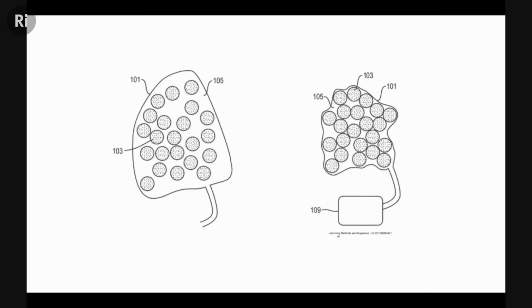Another phenomenon that we study in this phase change category is a principle called granular jamming. So granular jamming is like when you go to the beach and you jump on the sand and it's really hard, but when you play with the sand, it's really soft. Or if you buy coffee at the grocery store and it's a vacuum packed seal, it'll be really rigid, but when you open it, you can pour it out like a liquid. And that's because the particles get stuck. They jam and they have nowhere to go. And when they jam, they act like a solid. But when they have airspace and they can move around, they act like a liquid. So this is a way to go from solid to liquid and liquid to solid without temperature change. And it's infinitely reversible and almost instantaneous.